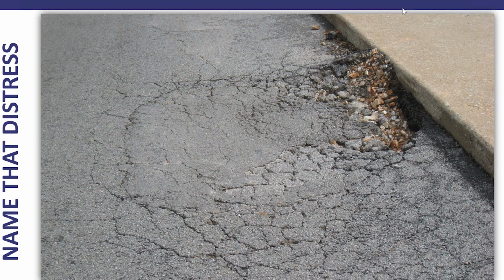All right, good answers coming in. Looks like we've got a subgrade failure, and that is most often due to water. So it's a low spot. We would possibly put this in the category of rutting because we do have a depression here. We also have the appearance of some fairly high severity cracking, looks like fatigue cracking because those cracks are interconnected, but it is in an isolated area.